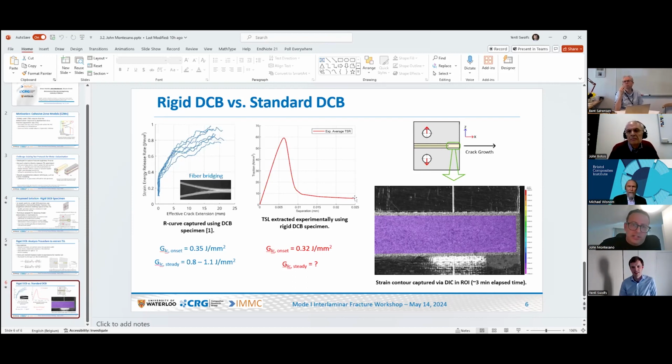But again, if you look at the full displacement, we actually displaced the samples beyond 0.025 millimeters. That's quite small. But again, we weren't able to quantify the energy release rate. So Bent, you want to follow up on that? Yeah, when I look at the numbers, you get a peak traction value of about 60 megapascal, and the drop off is less than 10 micron. That's the same order of magnitude that these guys I was citing got when they did the experiment in the simulation. Very comparable. And I think this was a glass fiber epoxy. So I think it's quite impressive that we hit about the same values for the traction separation law of the crack tip, which I find is one of the future challenges to address.